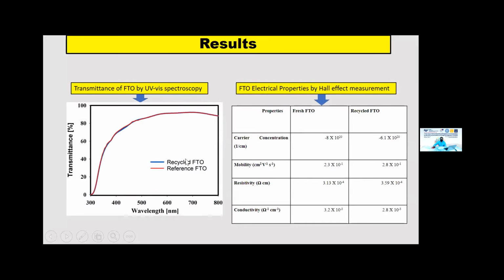And earlier we mentioned that if transmittance and absorbance are not good, we cannot get good quality, and we cannot get efficient electricity from the solar module. Because we use FTO for transmittance, we checked the transmittance of FTO by using UV-Vis, and there are no big changes between recycled and fresh FTO. This is the electrical properties, and we also ensure the quality of the electrical properties, with no big changes. So that can also ensure the quality of FTO.